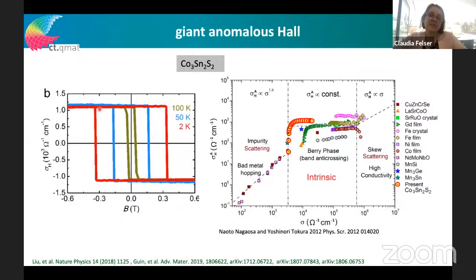Now it's a hard magnetic material. We see also in the Hall a very nice hard magnetic hysteresis of the compound. So this is the reason why we see the Weyl points also in ARPES. We can magnetize it outside of the chamber, and then have a magnetized sample in the chamber. And also here we can see the anomalous Hall effect. The large value is related to intrinsic effects coming from the Berry curvature.